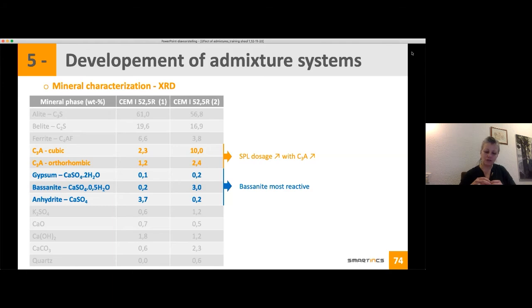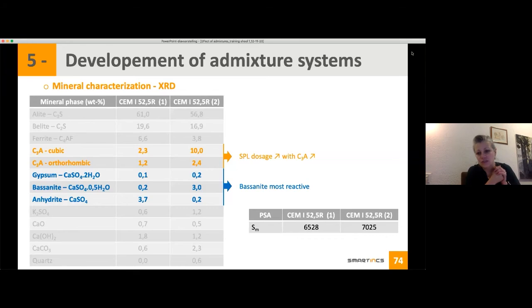So suddenly the surface area where the superplast can react is much higher. So you will need a higher dosage to get the same dispersing effects. Another parameter that also plays a role is your surface area. If you look in this specific case between the first cement and the second one, the specific surface area, measured with laser diffraction, shows that the second one is a bit finer than the first one.